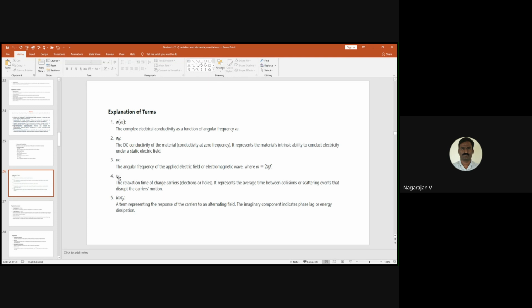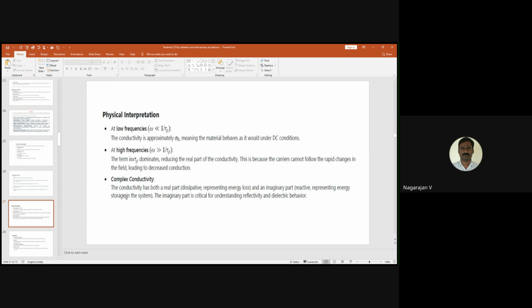Tau p is the relaxation time of charge carriers, which represents the average time between collisions or scattering events that disturb the carrier motions. The term i omega tau p represents the response of the carrier to an alternating field, and the imaginary component indicates phase lag, generally energy dissipation. The physical interpretation: at low frequencies, omega much less than 1 by tau p, the conductivity is approximately sigma naught. The material behaves as it would under DC conditions.